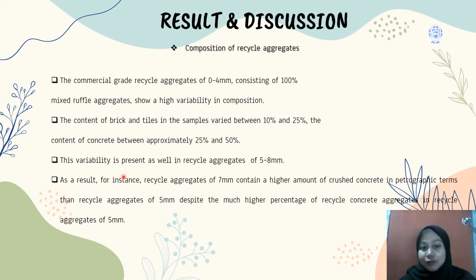This variability is present as well in recycled aggregate of 5 to 8 mm. As a result, for instance, recycled aggregate of 5 to 8 mm contains a higher amount of crushed concrete in petrographic terms than recycled aggregate of 1 to 4 mm, despite the much higher percentage of recycled concrete aggregate in recycled aggregate of 1 to 4 mm.